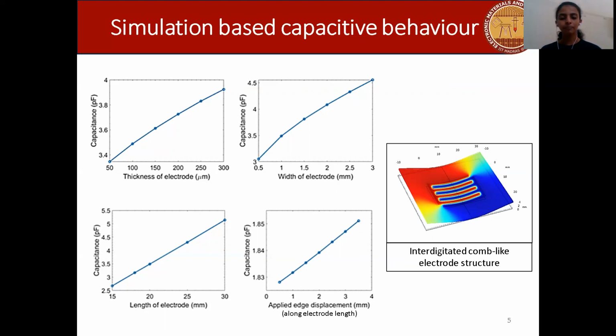This can be explained by saying that there is no significant difference in any of the parameters. For example, the gap between the electrodes is not significantly changing because of this bending. As a result, we cannot observe any significant change in capacitance. While on the other side, if we bend the structure about an axis along the electrode length, we can observe a significant reduction in the gap between the electrodes, because of which the capacitance value was observed to increase from 1.83 to 1.85 picofarad in this case.